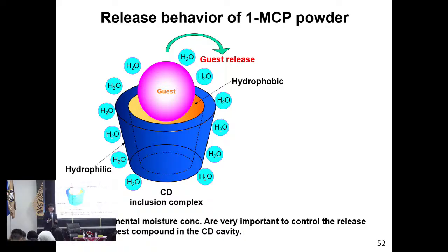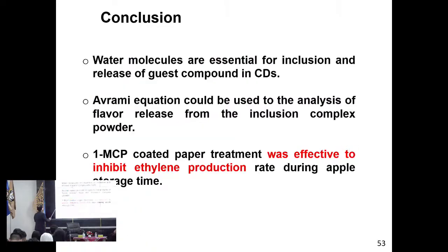Also, for spray-dried flavor powder, emulsion flavor spray-dried powder, when we want to see the release, we need the moisture. So relative humidity is very important. Environmental moisture is very important to control the release of the guest compound inside the cyclodextrin cavity. Moisture content is very important for both release and inclusion. So water molecules are essential for the inclusion and the release of the guest compound inside the cyclodextrin.